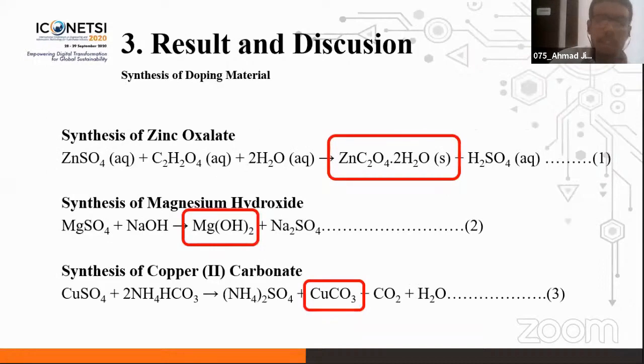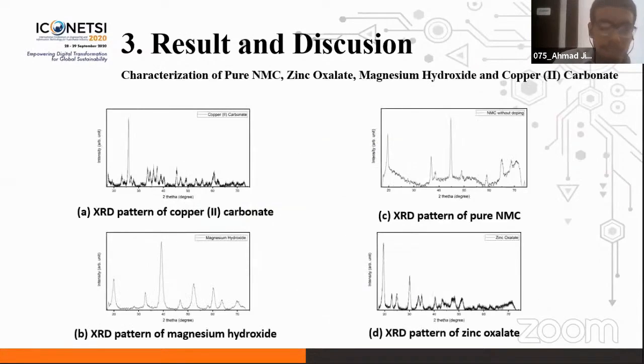Okay, this is for the result. For zinc oxalate, this is the result. And this is for magnesium hydroxide and copper(II) carbonate. The characterization of each material from figures A, B, and D is suitable with the previous XRD pattern. Thus, we can conclude that the synthesis reaction was successfully performed. And figure C can be attributed to the pure layered structure of NMC cathode material, matching the XRD pattern from previous research. Thus, this reaction was successfully employed.